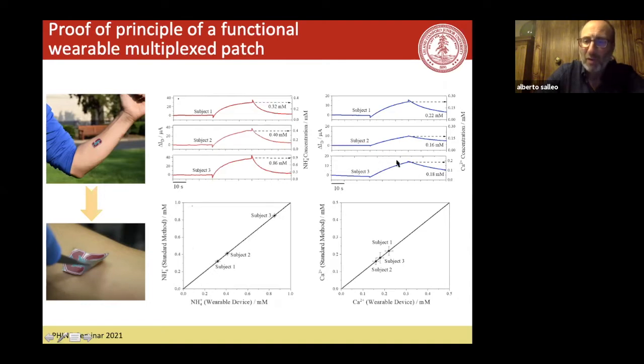And we did calcium at the same time, same thing. After we put a pulse for about 30 seconds, we measure the current at the end of the pulse, and the current is then translated into a concentration of calcium after the calibration curve is built. And then we check with our standard electrode that the concentration of calcium is what you expected based on what you get from the standard electrode.